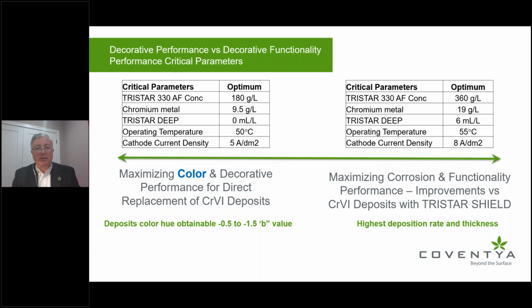If we want to maximize color, the blue color, for instance, we set up the decorative performance parameters, and we can achieve the blue color hue, LAB value, the B value of -0.5 to 1.5. And these are the properties. We're basically operating at lower chromium metal, and we adjust the complex and one of the other additives.